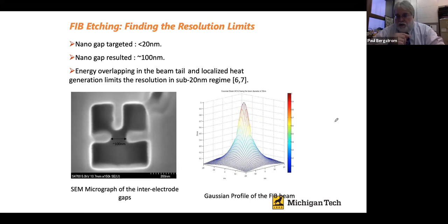And so this beam is raster scanned over the surface in order to produce the ablation of the material that we want, but this localized heating also causes an evaporation of materials. So if you have structures that are smaller than 20 or 30 nanometers, those structures self-heat so much that they basically evaporate in the vacuum and you're left with nothing.